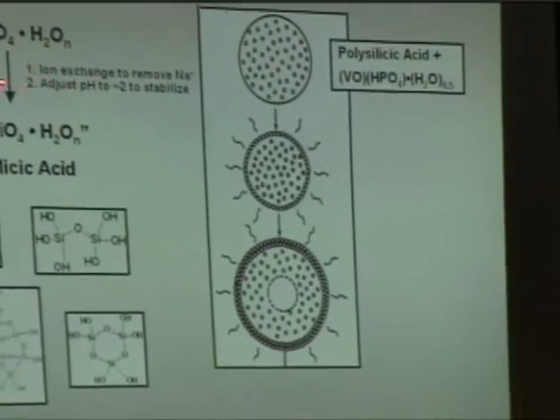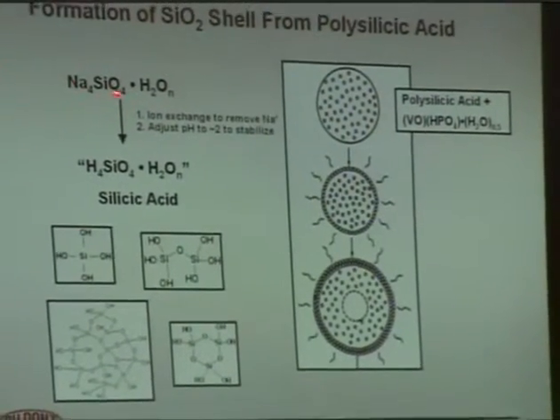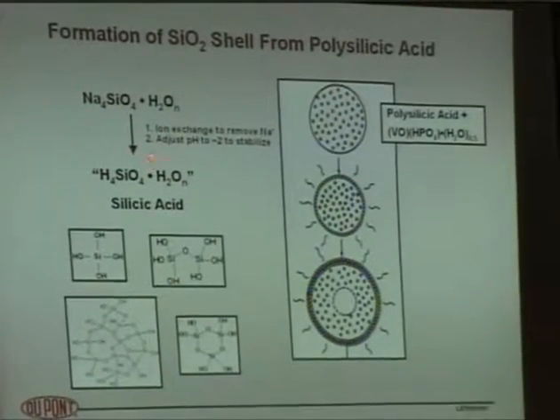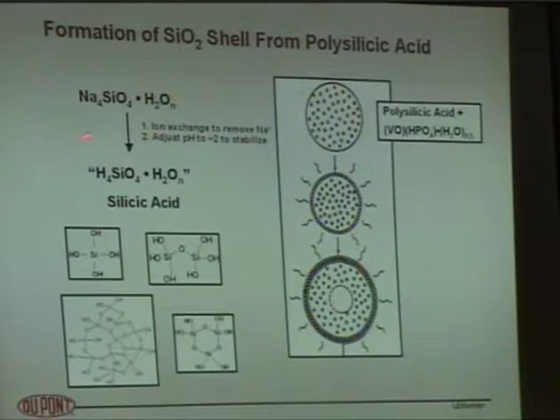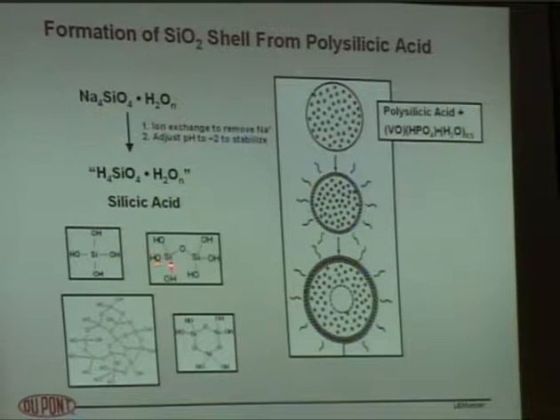And one of our silica experts, Horacio Bergna, found that he could take sodium silicate and ion exchange it. And this required, he had been with us for like 50 years, 50 years of experience to learn how to do this, to stabilize silicic acid, monomeric silicic acid. It wants to dimerize and trimerize and eventually give you silica very easily. If you don't treat it right, you'll end up with silica again. So stabilizing this silicic acid was critical.